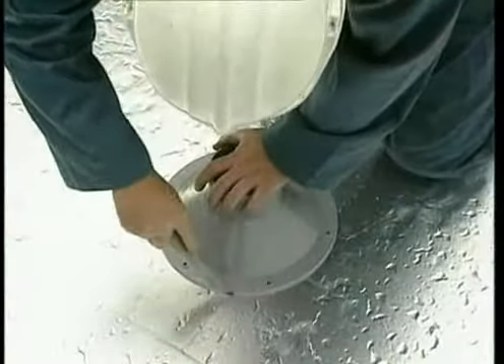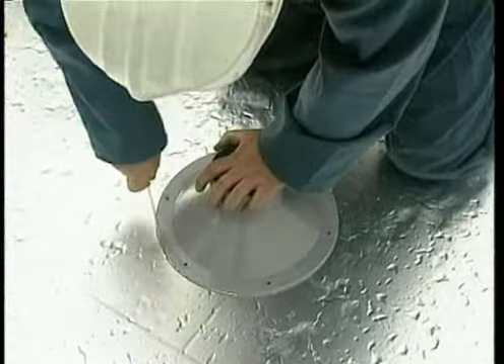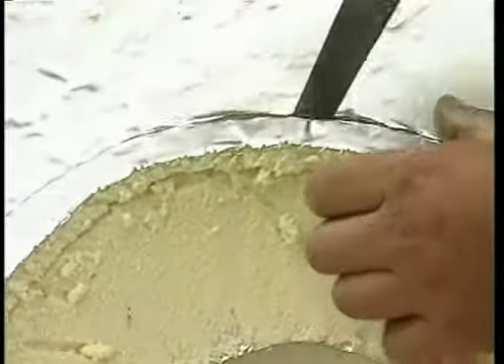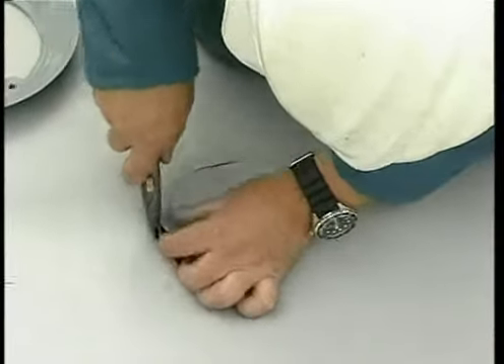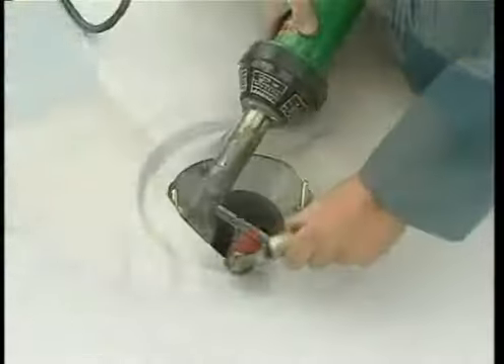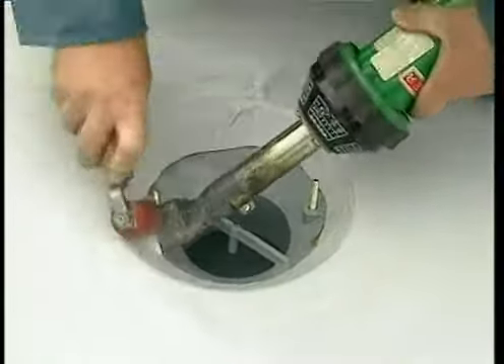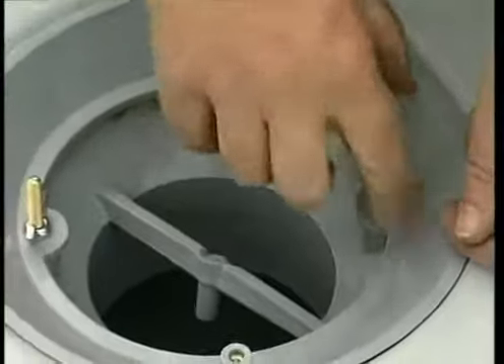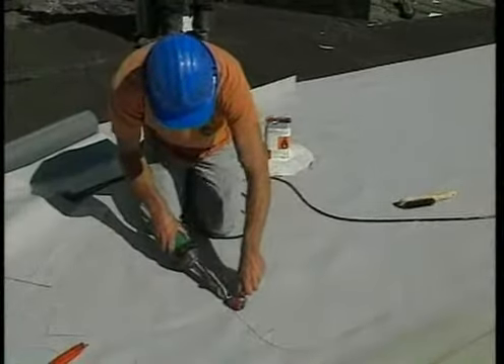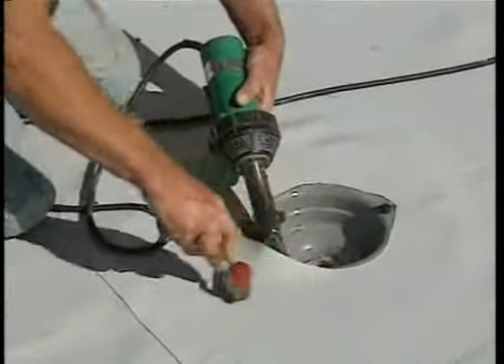Rainwater outlets are installed as work progresses. To ensure the outlet does not sit higher than the membrane, the insulation is recessed. The membrane is laid over the outlet and the aperture cut out after fixing. Both Alkorplan and Alkorflex can be welded to outlets manufactured from unplasticized PVC. Where other materials are installed, a clamping ring must be used to secure the membrane to the fitting. The roofing sheet is welded directly to the outlet, or in the case of fleece-backed sheet, a collar of unbacked membrane is welded to the roofing sheet and outlet.